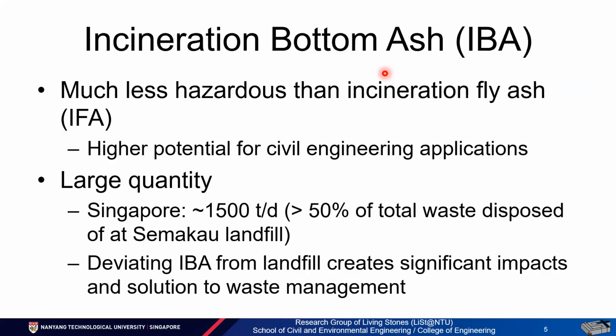Our research group mainly works on incineration bottom ash (IBA) for good reason. IBA is much less hazardous than incineration fly ash (IFA), and because of that it represents a higher potential for reutilization as civil engineering materials. We also understand IBA has a much larger quantity, typically more than 70 to 80% of the total ash generated. IFA represents a smaller portion.